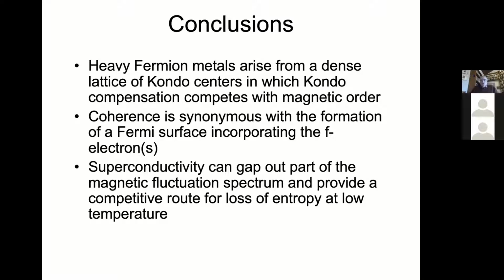So the idea is that heavy fermions, the general picture is metals arise from a dense lattice of Kondo centers in which you have essentially the Kondo compensation competing with magnetic order, and that coherence is synonymous with the formation of a Fermi surface incorporating the F electrons. And the interesting aspect of the superconductivity is that part of what it can do is it can gap out part of the magnetic fluctuation spectrum. And this provides a competitive route for the loss of entropy at low temperature.